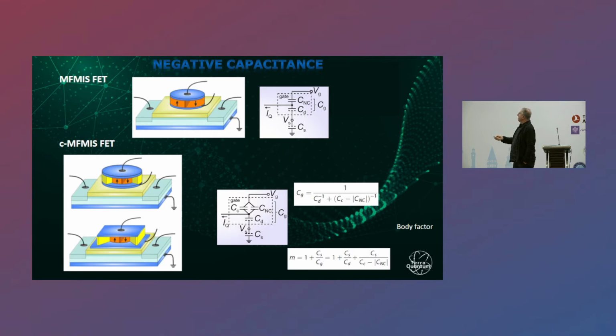Now, this is the device which we propose. It is just a capacitor with a ferroelectric inside, 20 nanometers in diameter, divided into two domains. Is it good enough? Not quite, because we can analyze its work a little bit and find out that once we've made it, its parameters are completely fixed. Because all the sizes are predefined, we cannot vary the characteristics of this transistor much.